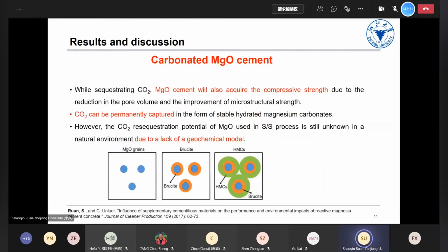First, about the carbonated MgO cement, we have published a lot of papers in this area. As we know, MgO cement acquires compressive strength by sequestrating carbon dioxide. This leads to a reduction in pore volume and an improvement of the microstructure. The carbon dioxide can be permanently captured in the form of stable hydrated magnesium carbonates. However, the carbon dioxide sequestration potential of MgO used in SS in a natural environment is still unknown, due to the lack of a geochemical model.